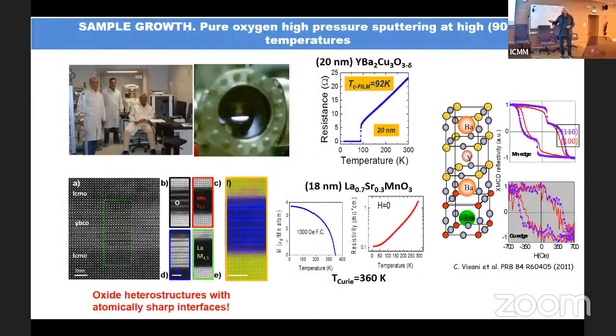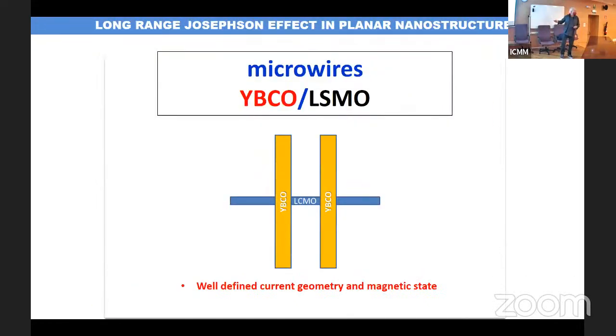So, the idea is making this kind of structure. Very, very simple, right? A manganite wire with two superconducting electrodes. But these materials, to grow properly, require structure and ground states. They have to be grown at very high temperatures, typically 800 to 900 degrees. So there is no process resist in nanofabrication that withstands this temperature. So it's a complex experimental problem.